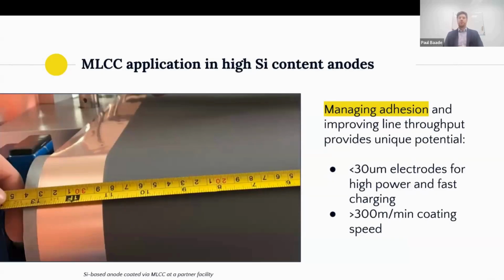The second example that I wanted to give was actually the one that we started with. And the simple reason why we did it was, if we move towards higher and higher silicon anodes, even 50, 60, 70, 80% of silicon content, the specific capacity is much, much higher in storage. So if you talk about target designs with 3, 4, 5 milliamp hours per square centimeter in terms of loading, your target electrode thickness becomes relatively low, maybe 30, 40 microns.